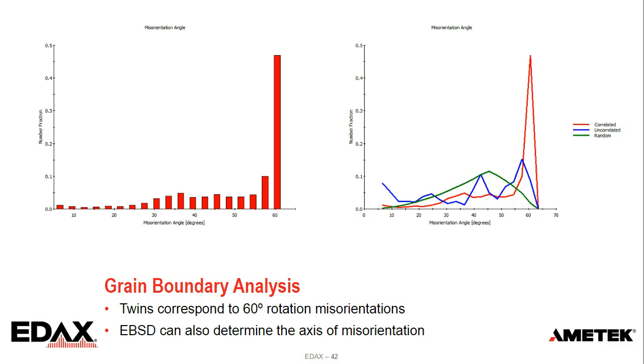We can also do some analysis there on the right, where we look at what we call the correlated misorientations. That's looking at the misorientations point to point. We can look at the uncorrelated, where we compare one point to every other point. And then we can look at what a random distribution would look like. So this gives us an idea of how the spatial distribution of those orientations influences the grain boundary